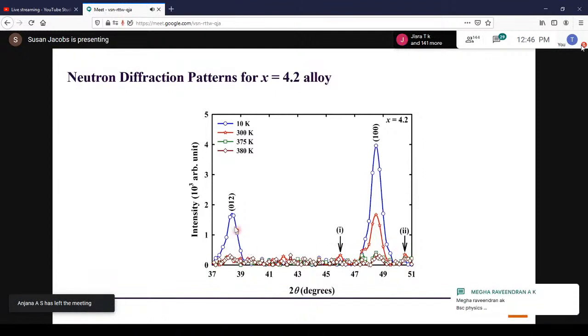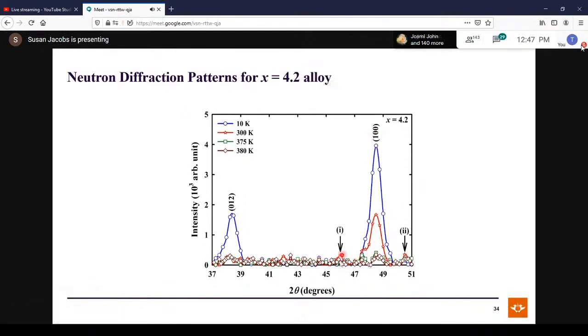Now, even in the 4.2 alloy, the charge order peak is still present. So therefore, what can we conclude? For 0, it was commensurate. There was only the single peak. But when you added vanadium, you see 2 satellite peaks, which means it goes incommensurate.